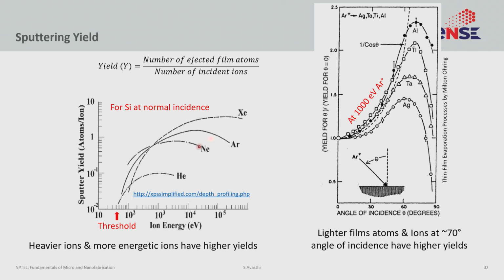For every sputtering atom though, there is a certain threshold, which is the minimum energy required to eject an atom, that tends to be something between 10 to 100 eV. Okay? Now, the sputtering yield does not just depend upon what you are using to do the sputtering, it also depends upon what you are sputtering. So for example, heavy metals like Ag tend to sputter at a lower yield, light materials like aluminum tend to sputter at a high yield.